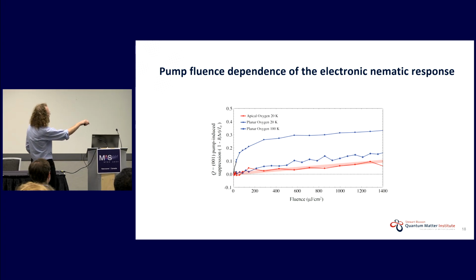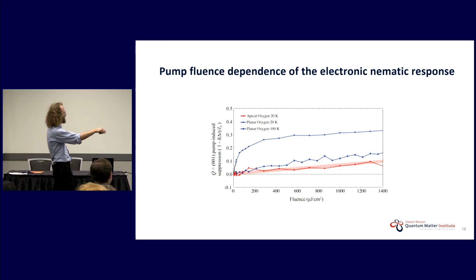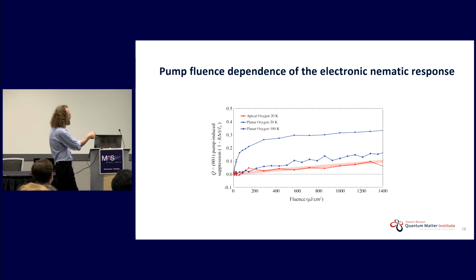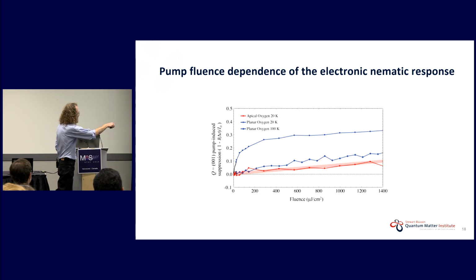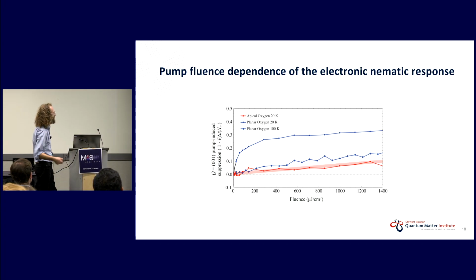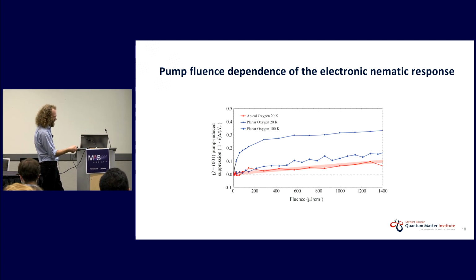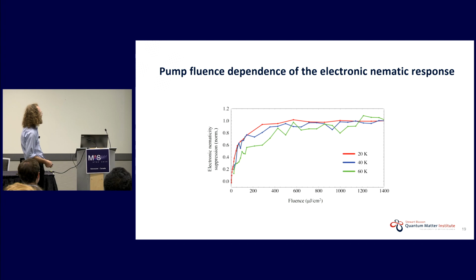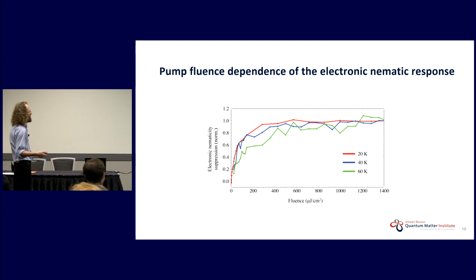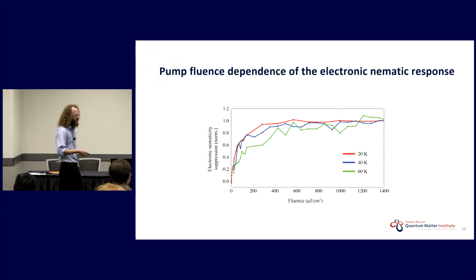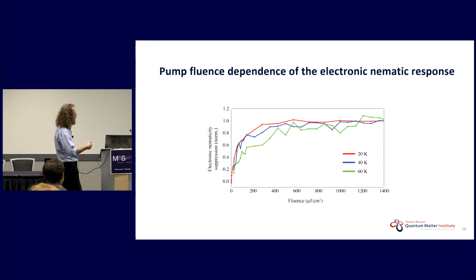So this here, 0 means no pump probe effect, and 1 would be a full suppression of the peak. Okay, that's what I'm plotting here. So then we just naively call this thing our background, okay? Fit it with a line and subtract it from all of our low temperature measurements. We have a bunch of them, and that's what I'm plotting here. And this is what I'm going to call the suppression of the electronic nematicity, or the suppression of the rotational symmetry breaking as a function of fluence.